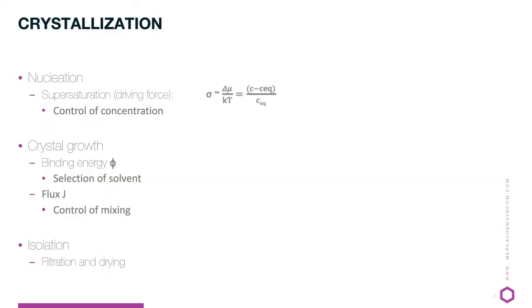Crystallization consists of two different steps. First nucleation, next crystal growth. Nucleation only occurs when there is a driving force. So a supersaturated solution will be formed, and that only occurs when there is a higher concentration present compared to the equilibrium concentration. So the excess of compound in solution will solidify at a rate that is related to this